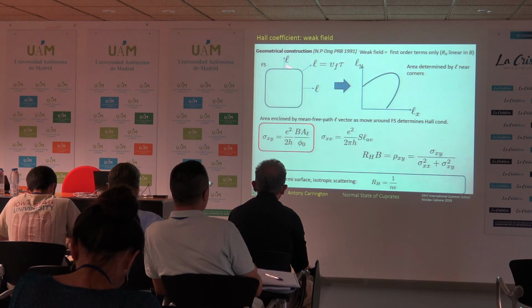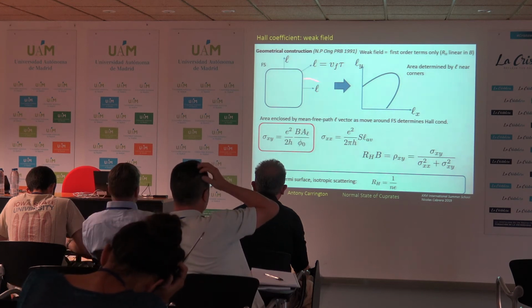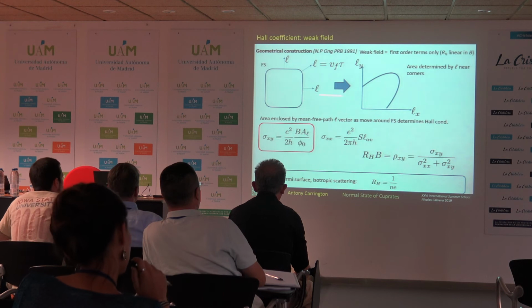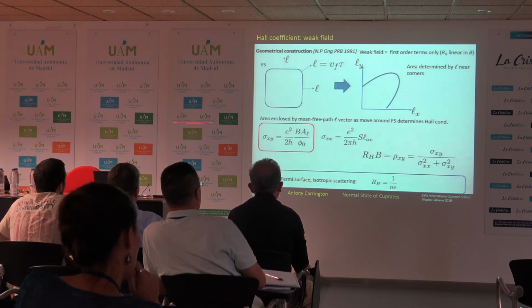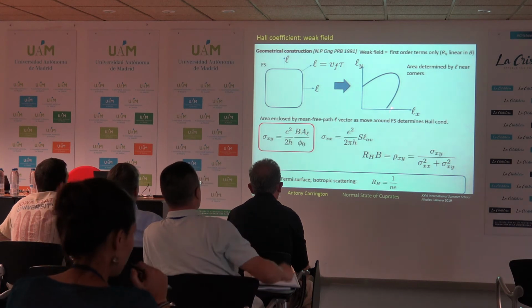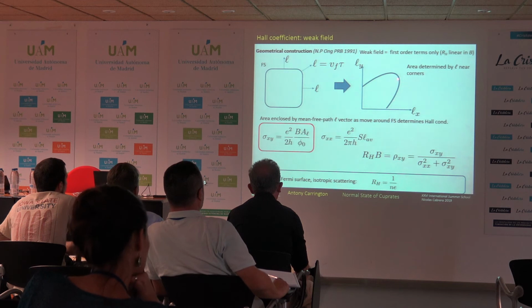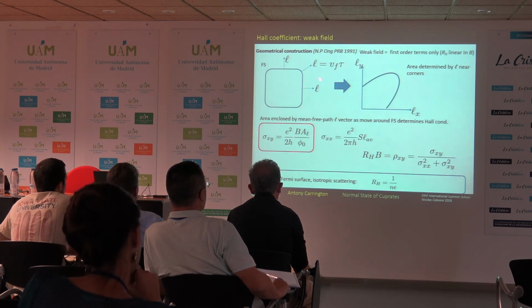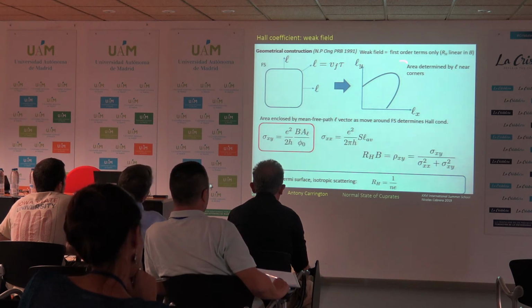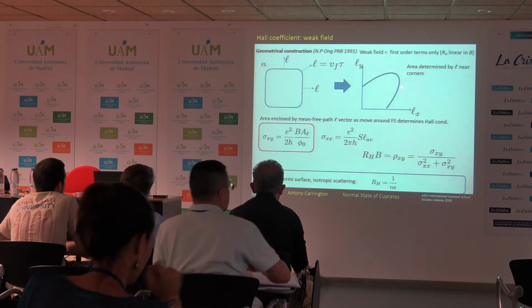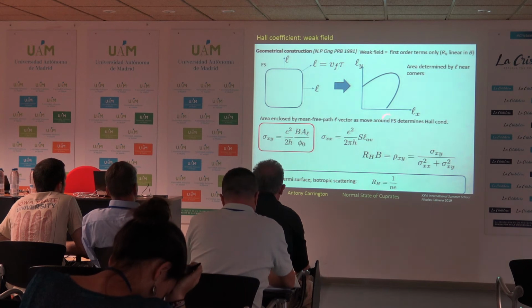Okay, and then as we go around the Fermi surface, we have a mean free path vector. So this is just v_F times the scattering time, so l. Okay, and you can see that here v_F is always going to be perpendicular to the Fermi surface, so here it points in this direction, here it points in this direction, and here it points in the 45-degree direction. And then what you do is you map out what happens to this l vector as you move around the Fermi surface. Okay, so here we'd start off right here, and we'd stay there all the way until we get to right about this point here, at which point we go around here, and then end up back here again. So we trace out this curve. Now in general, this could trace out quite a complicated curve. It can trace out a curve that's got multiple loops in it, but I'll just take a simple example here.